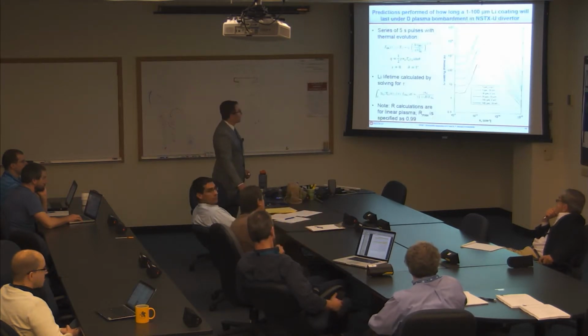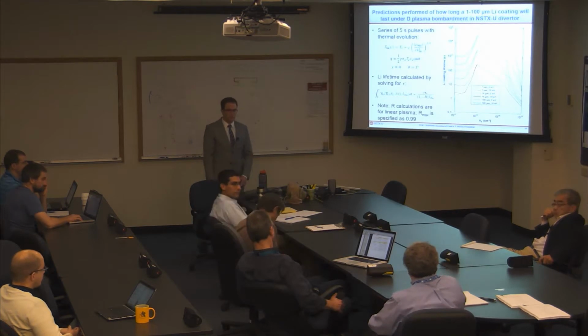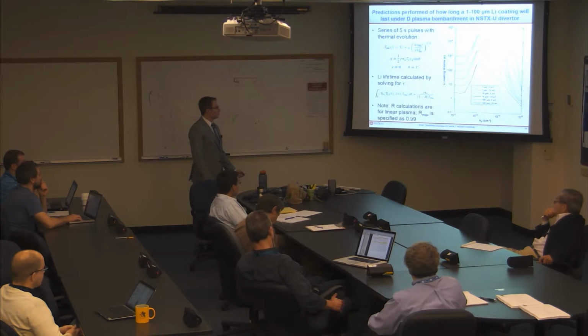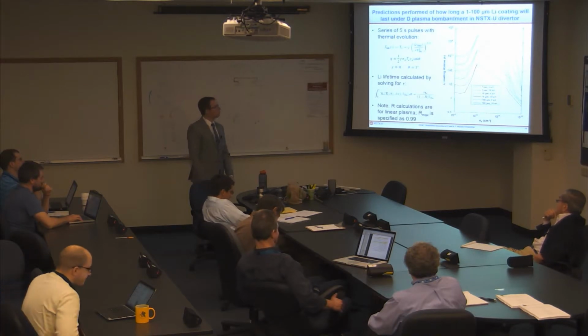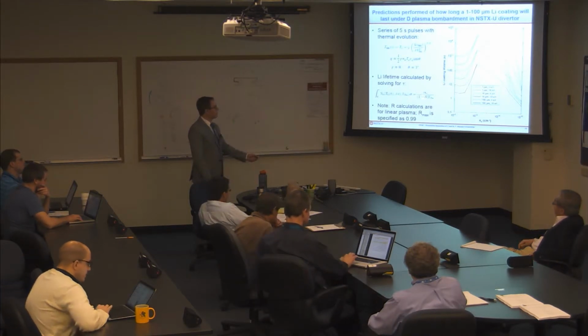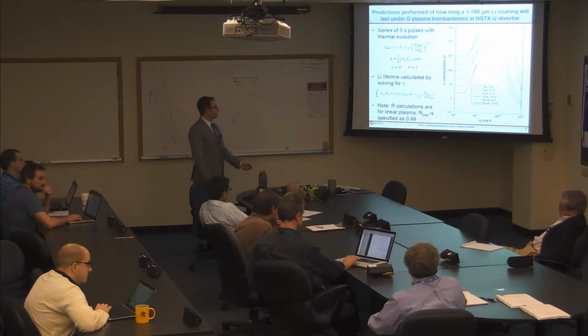And then finally, everything is really dependent on this R max specified at 0.99, especially between 10 to the 13 and 10 to the 14. Sure, it's proportional to 1 over 1 minus R, if you solve this for tau. So if you go to 0.999, then it increases by a factor of 10.